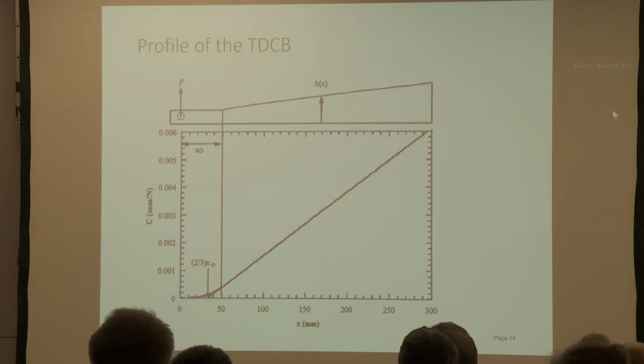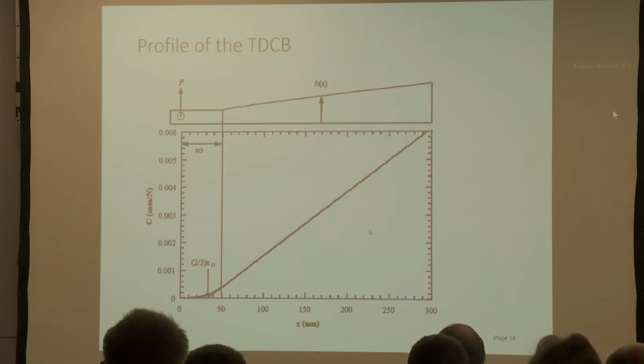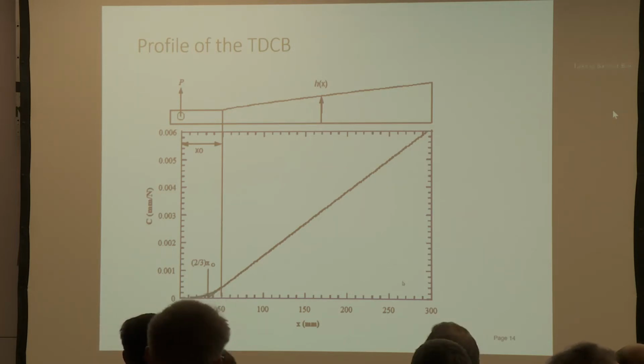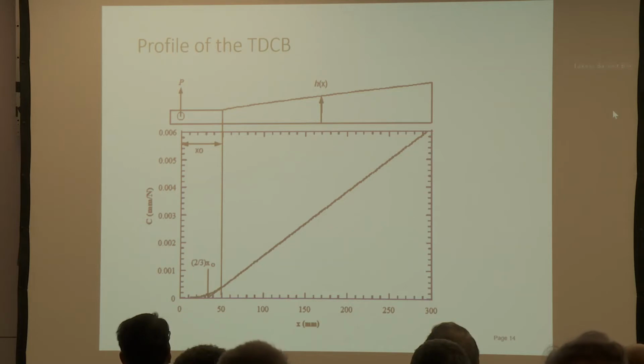So when we revisited this very popular ASTM test method, we looked at two issues in this test. The first issue was that the contoured part of the beam, that part which is tapered such that m is held constant, doesn't extend for the whole length of the beam, but is discontinuous. And you can see that leads to a compliance error, if you like, in the early part of the beam. So the straight flat part of the beam, which we say here extends x0 from the load line, basically has a different compliance characteristic to the rest of the beam. So that needed to be recognized.